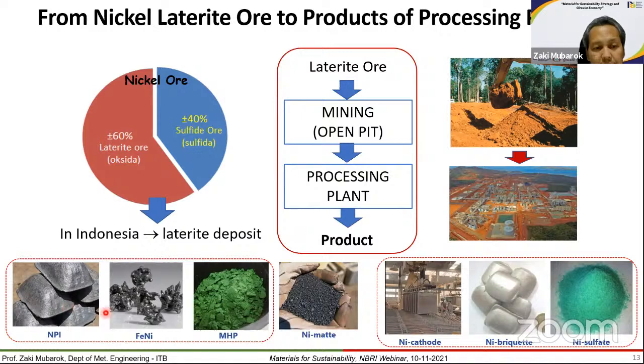Started from nickel pig iron, we have a lot in Indonesia. Ferronickel, we have a plant long time ago, owned by Antam since the end of the 70s, and MHP is just recently produced, nickel matte since long time. And nickel cathode, nickel briquette, nickel sulfate, and the left part is classified as class 2 nickel, which means the nickel content, the purity, is low, like nickel pig iron is only 15%, and the objective of producing nickel pig iron is basically for stainless steel, which contains mostly iron. And the right part is class 1 nickel: nickel cathode, 99.99%, nickel briquette, and nickel sulfate with 99% purity up, which is utilized for battery.